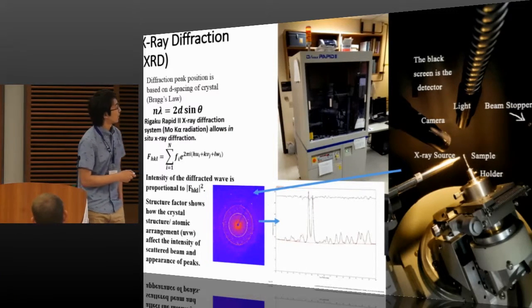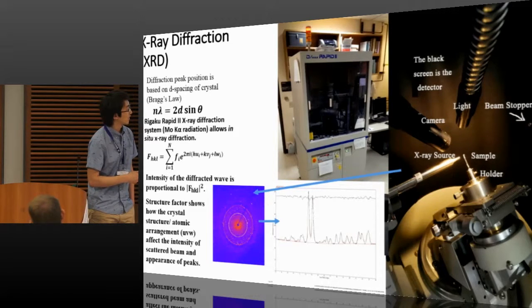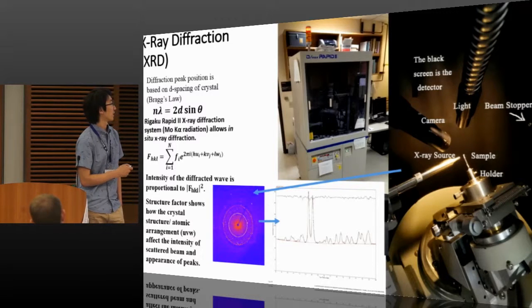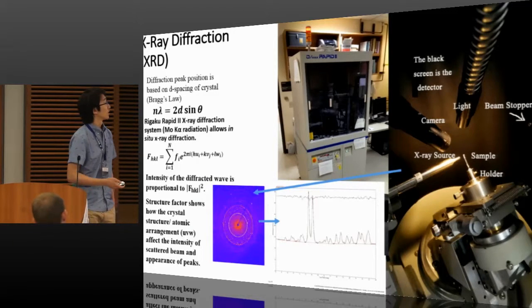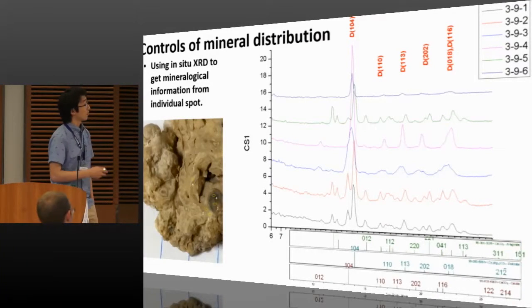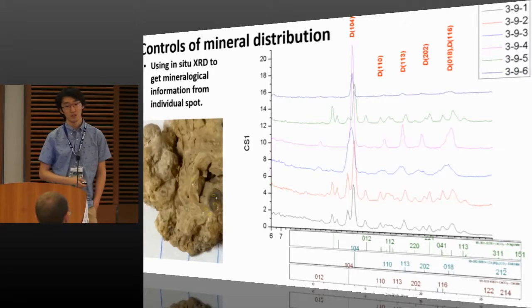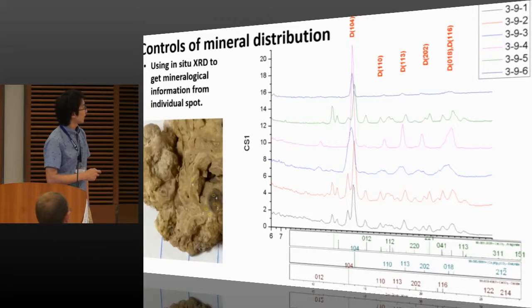So you have the X-ray source here and the hand sample, and then it's scattered based on Bragg's law at different angles. And then we collect that in the detector for the 2D diffraction pattern, and we use software to convert it back to 1D, so it's easier to analyze. Because this machine can do in situ XRD, we can actually pick individual points from the rock and then examine the minerals inside of it.